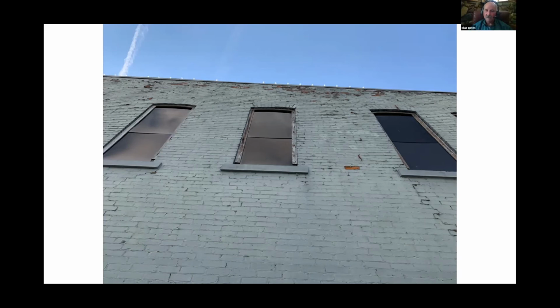So, not recommended for brick. The way we fired brick back in the 1800s was in a tunnel type kiln, and the outer face got the most vitrified, went from clay into pottery, we'll call it, terracotta, etc. So the outer face is the most durable, hardest face on the whole brick. Once you remove that, now you're really opening up the brick to a much greater absorption and rate of deterioration.